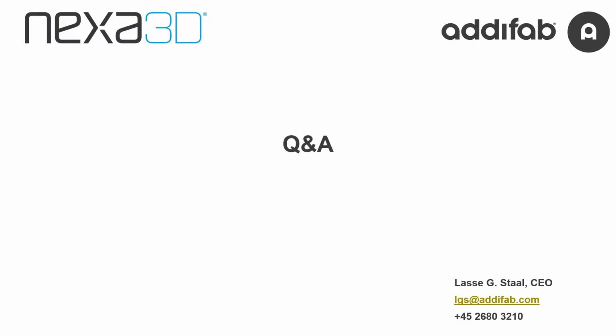Max asks, what is the dimensional tolerance of the tool or the plastic part coming out of the system? We usually expect a tolerance of plus minus 1/10 of a millimeter on the first iteration we do. Depending on the printer configuration, we can step from 75 micron down to 10 micron resolution. And that means that if we need to do finer tolerances, we will usually do a second iteration to tweak mold designs to take up any out of tolerance dimensions.